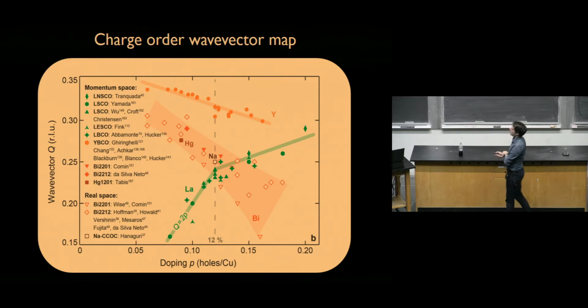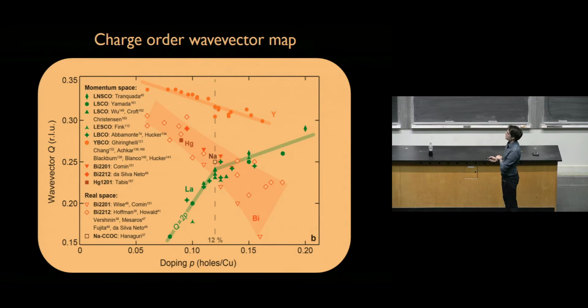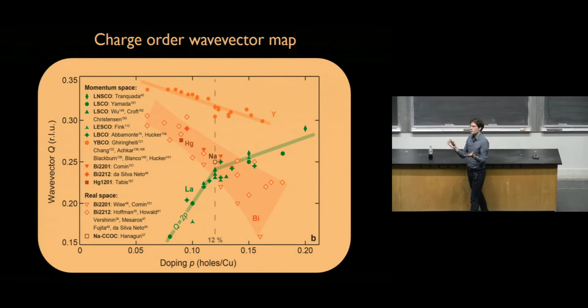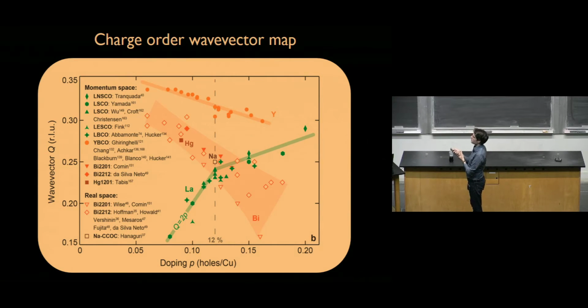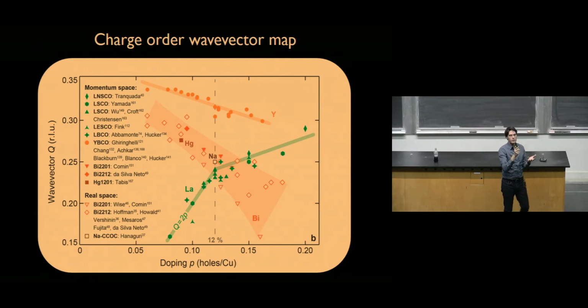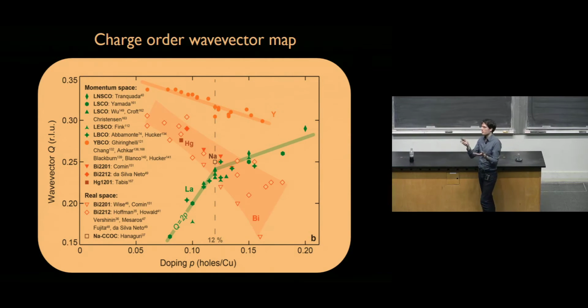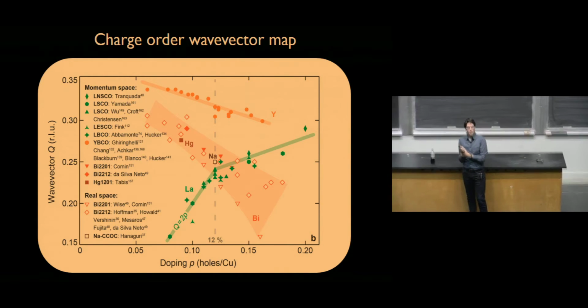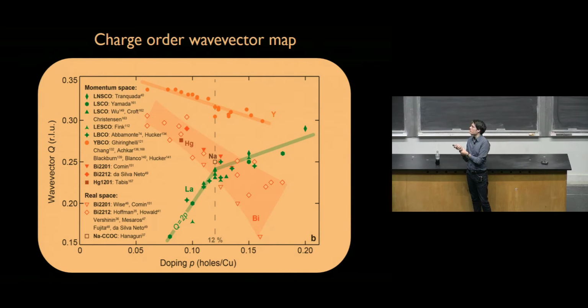And this is a similar map, again plotted versus this kind of phase diagram, as a function of doping. But now I'm plotting the wave vector, which is 2 pi over lambda. So it's 2 pi over the period of charge order, in reciprocal lattice units. So 0.33 means a period of 3. So the wave vector is 1 over 3, 0.33, which means a spatial period of 3. Here, 0.25 means 1 over 4, so that's a spatial period of 4. So that tells you the wavelength of this wave-like modulation of the electronic density in your superconductor.